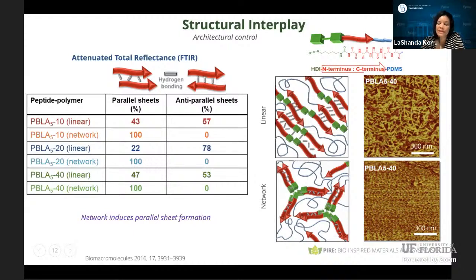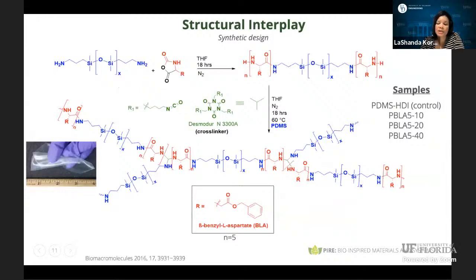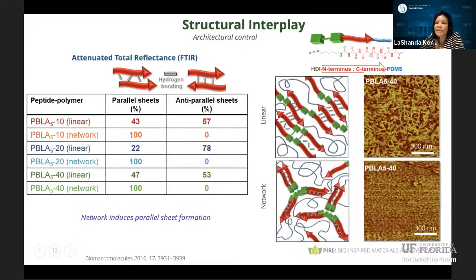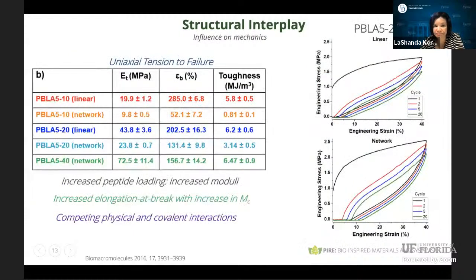And this is really due to the synthetic consequences of how we actually build up our covalent network in these systems. Basically, you have N-terminus to C-terminus of the systems, which then forces it into this parallel beta sheet conformation. Now, what are the consequences of this? So our linear system, as I showed on the previous slide, has a really nice, highly dense, percolating fiber network system, which gave really nice mechanical properties. However, our network system, driven by this fact that we have these parallel beta sheet structures, actually forms more globular structures. And you can see here in terms of drawing a circle around these, this is really identifying why you get more of these globular structures in the system. And we would anticipate that they would have very different mechanical properties, which is true.